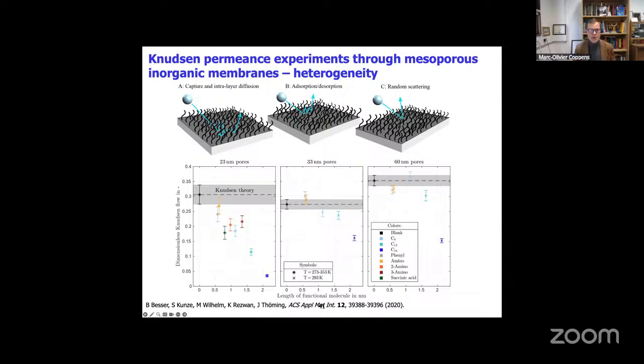And so they constructed these mesoporous membranes with brush structures on them with different functional groups of different lengths, and found that the Knudsen theory needed indeed to be corrected. So in this case, it's not just geometric roughness, but it is also the interaction of these molecules and how this leads to extra trapping alongside the walls. And so they show good agreement with that model that we proposed several years ago.